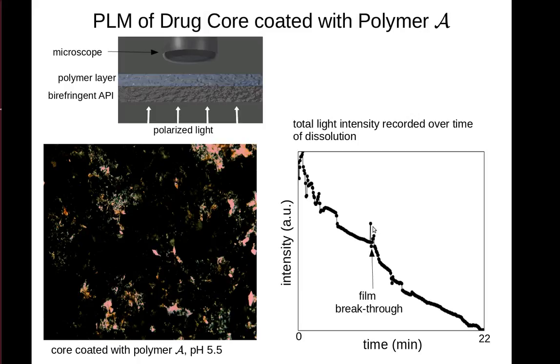We can study to some extent the dissolution of the API underneath the polymer film using some techniques. Since we know that the polymer film swells considerably with water, we expect that there might be some dissolution of the underlying API before the polymer is completely dissolved. One technique to try with this would be using polarized light microscopy. In this setup, we cast the core material on a microscope slide, then we spin coat a polymer layer, and we view the dissolution of the measurement under polarized light.